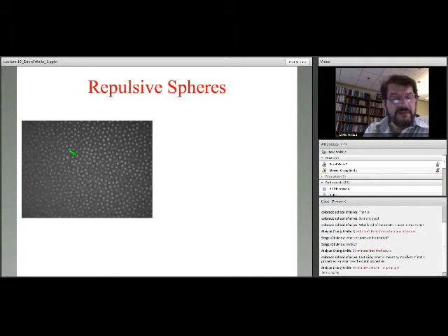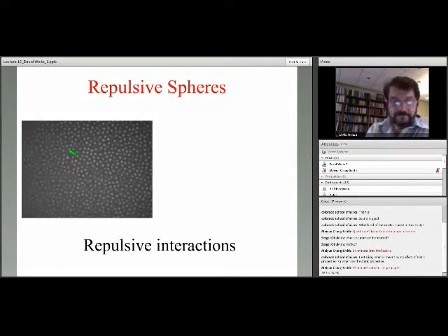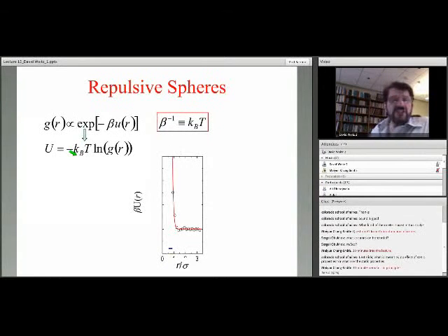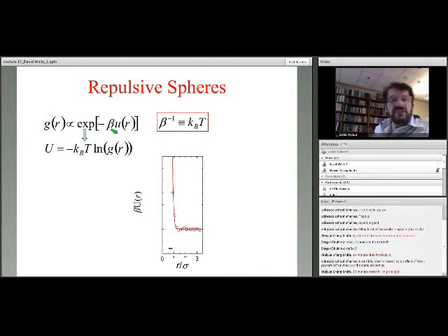You can actually measure the nature of the repulsive interaction by just recognizing that if you plot the separation between the particles, that's set on average by the thermal energy, because it's just distributed by the thermal energy. And so you can write the interaction as just the logarithmic distribution of the particle separations, and that's related to kT as shown here.